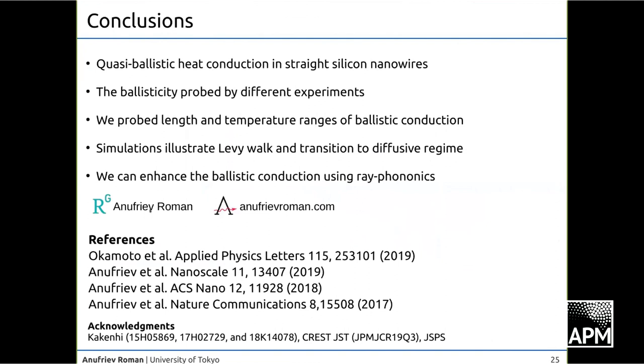Still, of course, we were not able to demonstrate anything like a perfectly 100% ballistic conduction because it's not really physically possible, I think, at room temperature. Still, we could see some trace of ballistic conduction, and we could probe it by two different methods, by the straight nanowire and by the bent serpentine nanowire. Yes, and we probed the lengths and temperature ranges of this conduction.